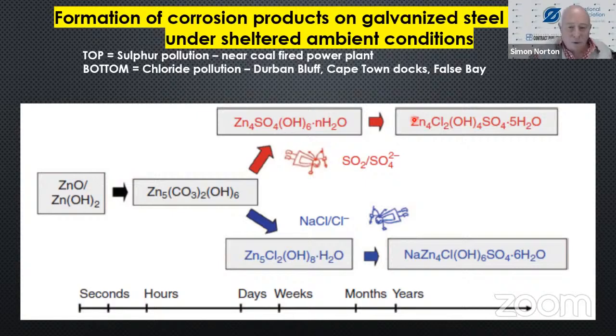What is happening in the rest of the world is that because sulfur dioxide and sulfates are being removed from the atmosphere, this mechanism here is no longer as prevalent as this mechanism at the bottom, which is near the sea or near an environment where there are chlorides. So the bottom mechanism is more applicable to South Africa. Chloride pollution: Durban, at the Bluff, along the coasts, Cape Town docks, False Bay coast in Cape Town, and other areas, the West Coast, Namibia, Walvis Bay, Lüderitz, all the coastal areas of Namibia. If you expose galvanized steel in that environment, you'll go this route.